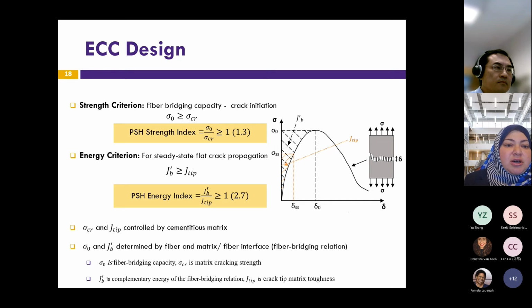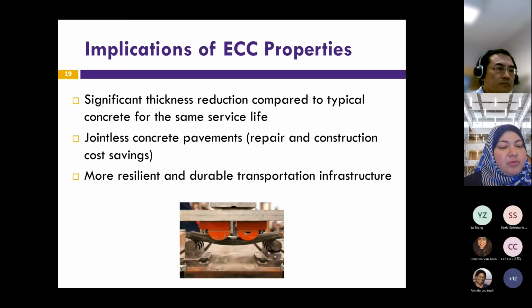The energy criteria, on the other hand, requires that the complementary energy of the fiber bridging relation, what we call J_b prime, is greater than or equal to the crack tip matrix toughness, J_tip. If we can satisfy both criteria, then we will get the pseudostrain hardening behavior, and we will get bendable concrete.